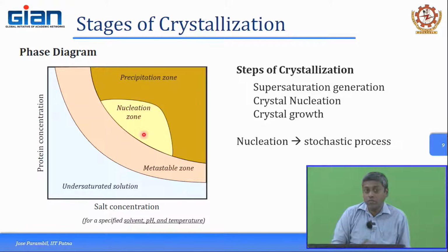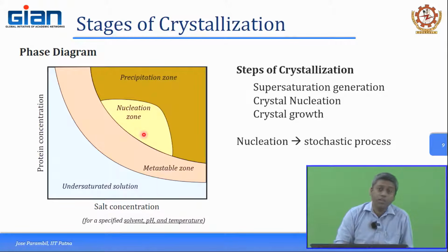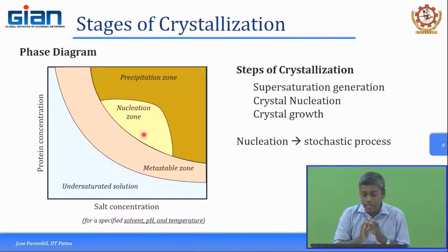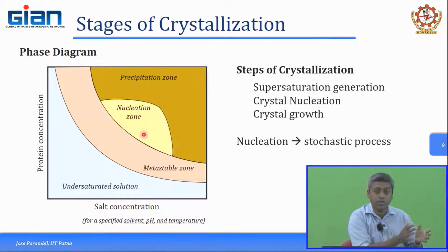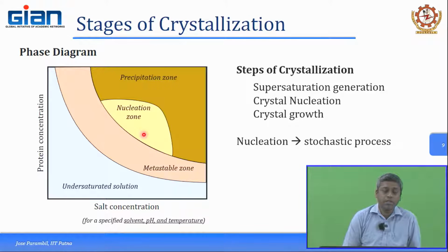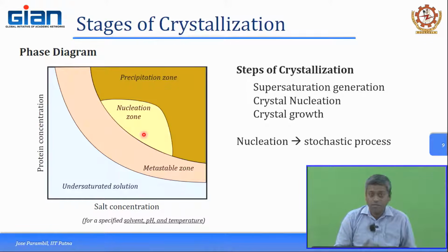So, when will it crystallize? Yes, thermodynamically it will crystallize, but how long will it take to crystallize? This is not something that you can easily predict or control. So, that becomes a very probabilistic event, which becomes harder to control from the process operational perspective. In the sense, if you are using a batch vessel, how long do you wait for the crystals to appear? You are generally expecting the crystals to appear in maybe an hour. In one batch it does not appear for 1 hour, you wait for another half an hour. How long will you have to wait?